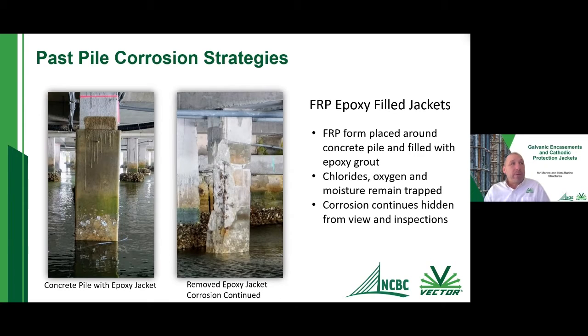And what ends up happening is moisture is still present in there, chlorides are still in there as well, and corrosion ends up actually occurring behind that fiberglass jacket. And it's very difficult to see any of the damage that's being done behind it until it gets extremely bad. If you can see here on the left, this is a jacket that was removed just a couple of years ago, and that was what was behind it. It wasn't evident that there was a huge amount of corrosion taking place, but once the jacket and the epoxy fill were removed, then you could see all the corrosion that had been taking place.